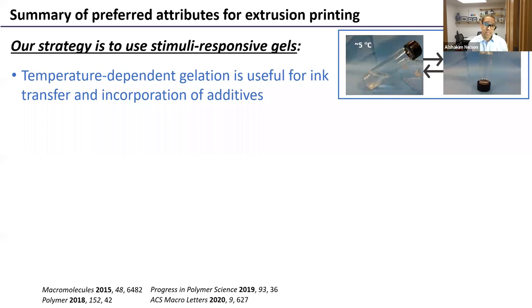And so this is really nice, because this allows us to introduce the cells into the gel homogeneously. Right, so we cool the gel down, it becomes a liquid, we add the cells, we stir it up for homogeneous distribution, warm it up to room temperature again, and then it's ready for printing.